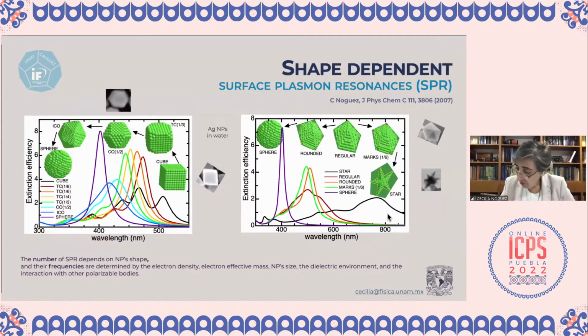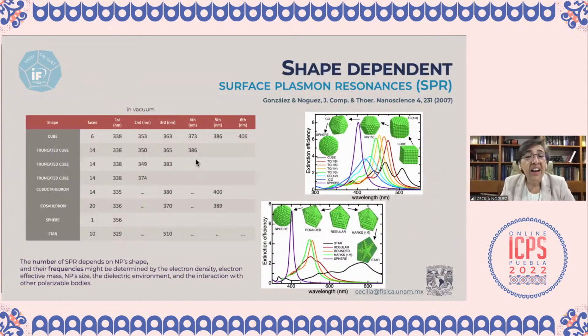So, for example, okay, depending on the shape of the nanoparticle, we can have 6 faces, and we can find, for example, in this case for the cube, 6 different surface plasmon resonances. For the truncated cube, now we can see only 4 resonances, and so on. And for example, for the star, we can have a lot of resonances that it's quite difficult to identify in this case.